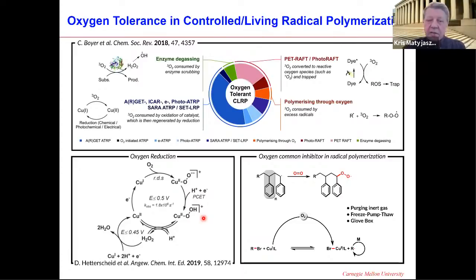What happens with oxygen as such? There was a beautiful review by Cyril Boyer approximately 2 years ago when he analyzed many papers on oxygen tolerance. So some of them, probably the majority, are with different types of ATRP systems. And very interesting and intriguing is PET-RAFT, which involves both energy and electron transfer reactions. You may also have something related to enzyme degassing, as we discuss in a moment. And sometimes you can have even polymerization through oxygen. So oxygen reacts with the organic radicals and forms peroxy radicals. And these peroxy radicals are rather stable, but still can react with the monomer and get incorporated. You can eventually produce polyperoxide, which may be a little bit challenging in handling, of course.